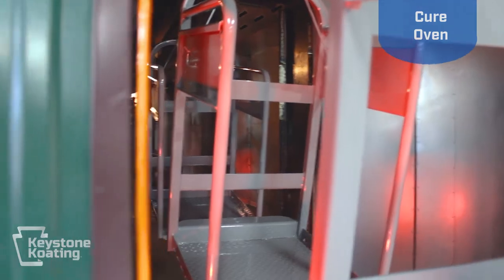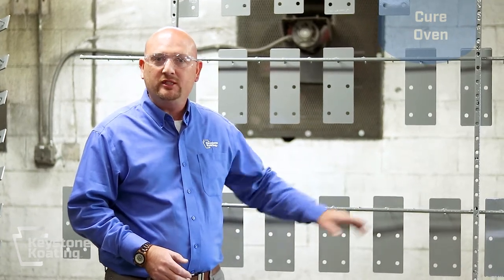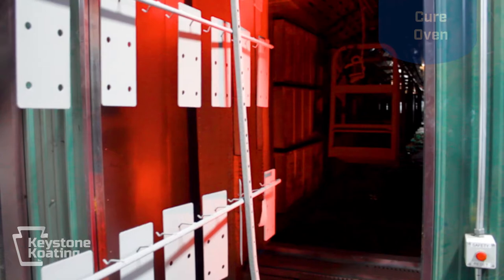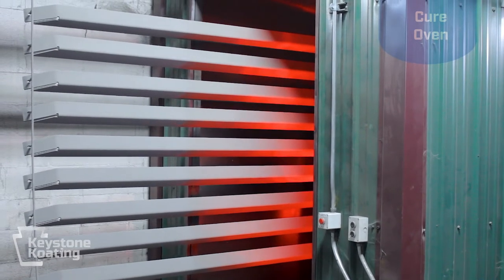As the parts come out of the top coat booth, they then move into the cure oven. Time and temperature in the oven varies depending on what powder we are spraying as well as what part we are spraying. Every powder comes with a recipe — it may say 350 degrees for 15 minutes, or 400 degrees for 20 minutes. In powder coating, we need to make sure the metal reaches the specified temperature for the specified length of time. If we're coating thin sheet metal, it moves through the process very quickly; if we're coating a heavy cast iron part, it slows down. Our temperature and line speed are constantly being adjusted to make sure that our powder is fully cured.